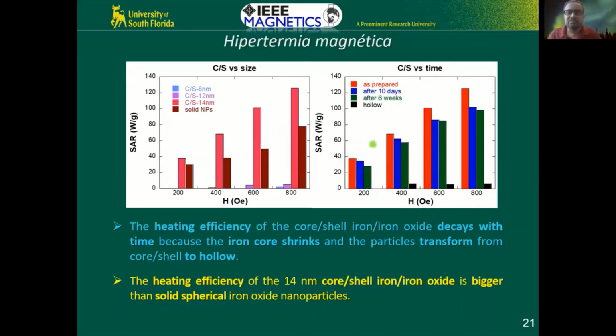However, our happiness was short-lived because if you look at this as a function of time, we did this over many days and weeks. It turns out that because of this Kirkendall effect, the core shell particle was continuously transforming into finally giving you a hollow particle. And of course, when it becomes a hollow particle, it doesn't heat up anymore. The SAR is non-existent.